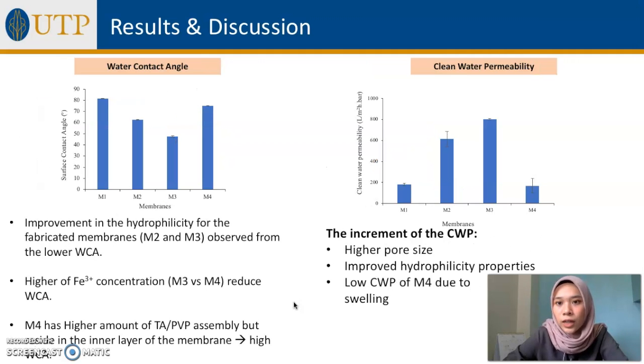Then moving on to the surface contact angle, the water contact angle for the modified membranes M2 and M3 is improved, indicating improved hydrophilicity.